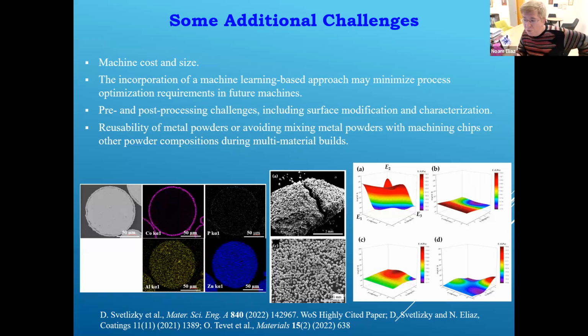So we had to do some surface functionalization to make the zinc-based powder hydrophobic, and then develop in-house shell technologies, both metallic and non-metallic. On the left-hand side, you can see cobalt phosphorus. You can see the X-ray mapping just to see that we got a nice shell, and the bright field image. In the middle, you can see SEM images of another surface modification process that we developed in-house, in this case alumina on top of the zinc aluminum.